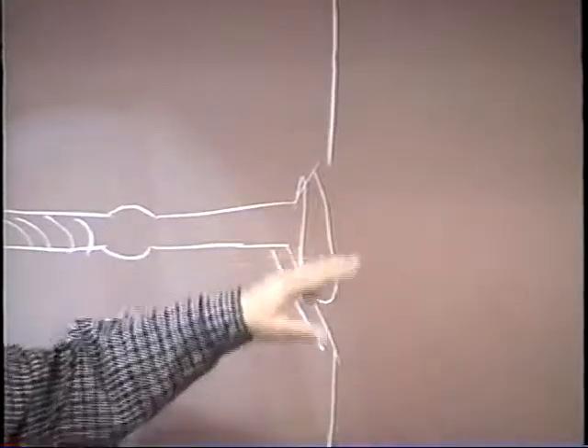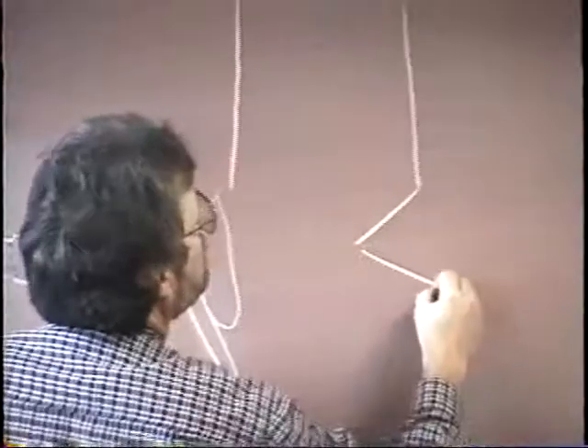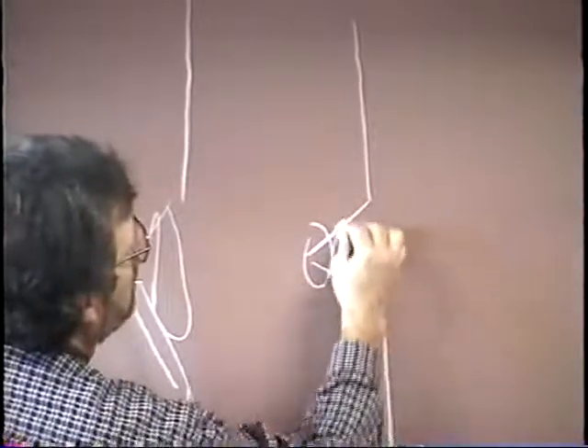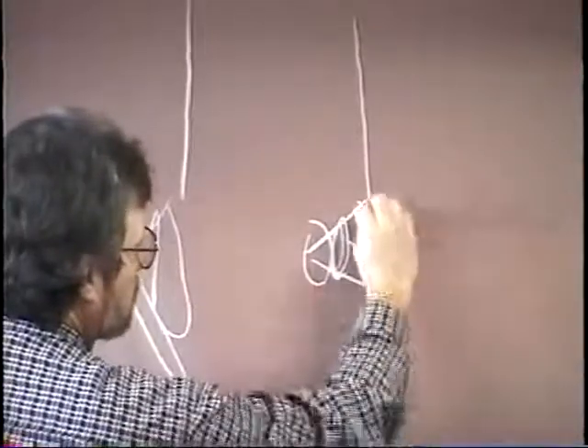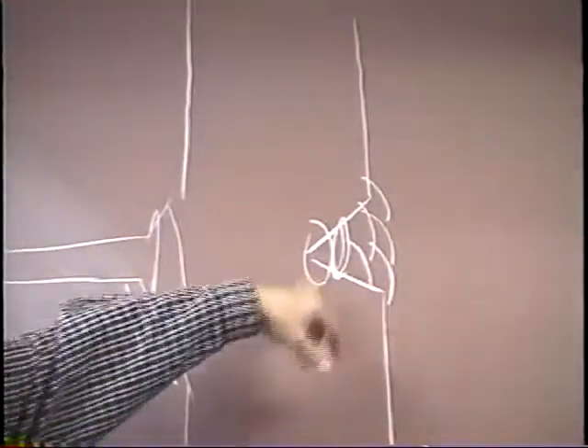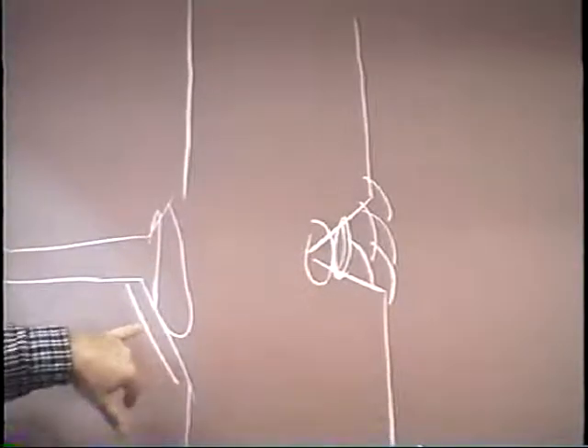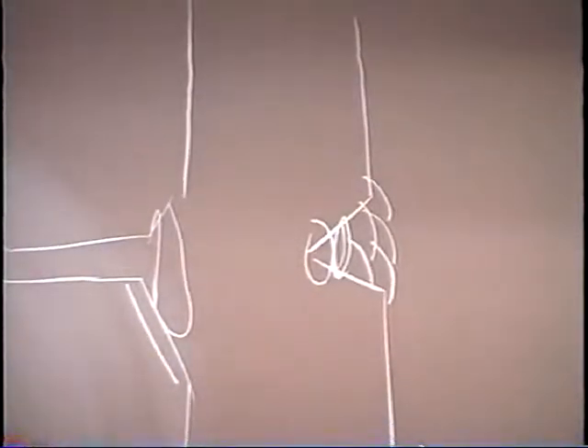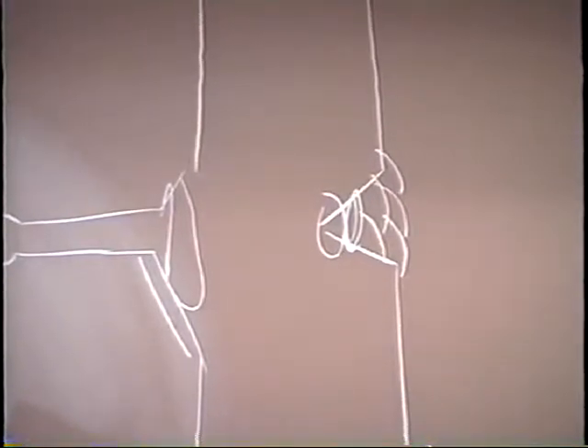That's overlap. So usually I'll only allow weaving on the hot pass, on the second bead. If you've got your first bead in like this, and your root bead is in, then you can use the W technique here to put that first pass in. After that, everything goes to stringer beads. If you try to weave beyond that, then you're going to get this type of overlap. Proper term is overlap. You'll hear people call it cold rope or cold lap. Those are improper terms. Proper term is overlap, as defined by the American Welding Society.